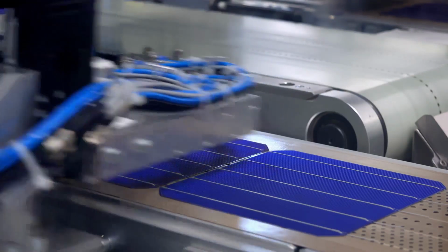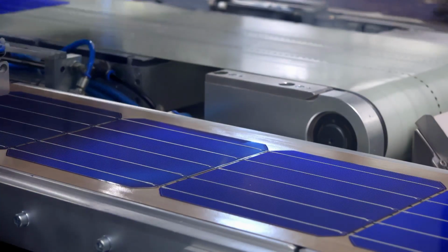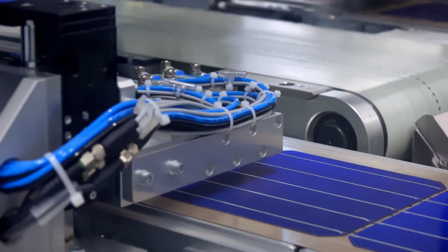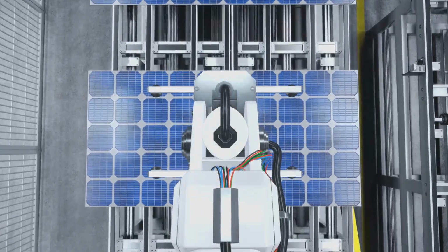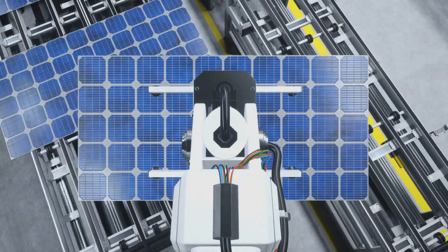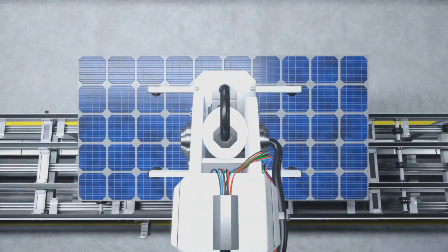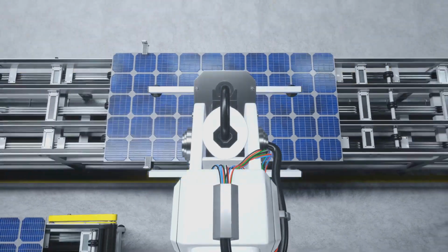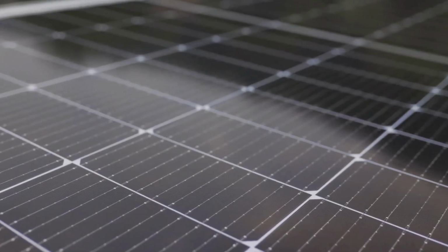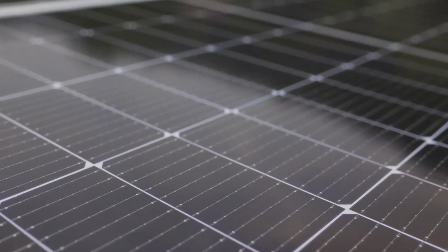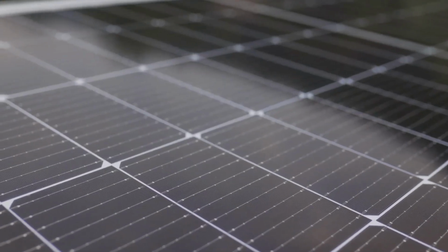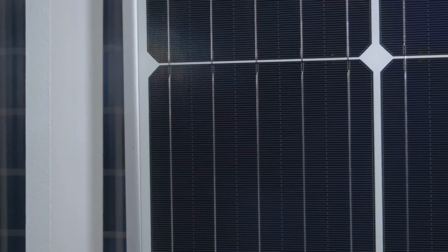About 99% pure, metallurgical grade. For solar, we need far purer. Using the Siemens process, silicon reacts with hydrogen chloride to form trichlorosilane. It's distilled, like refining alcohol, to remove impurities: iron, aluminum, boron. Then the ultra-pure gas is decomposed over heated silicon rods, slowly depositing ultra-pure polysilicon. After hundreds of hours, we get large, metallic-looking rods, our true starting blocks.